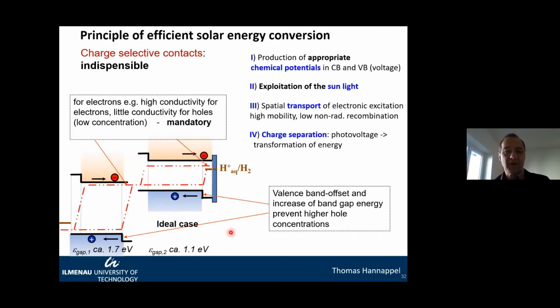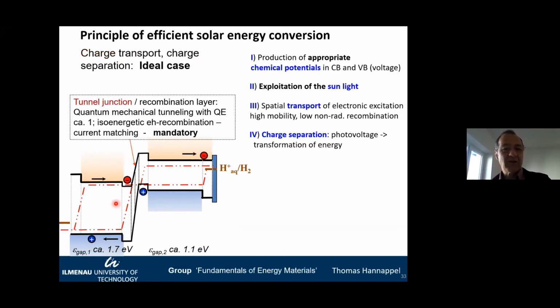Can just suggest to study this. Then also we need tunnel junction, where Esaki got a Nobel Prize for the invention of the so-called tunnel junction. And then we have the perfect device, as you can see, with very good photoabsorbers, with very good charge selective contacts, and with a perfect tunnel junction here, where we have isoenergetic recombination. And if everything is perfect, we can reach highest efficiencies up to 25 or even higher solar to hydrogen efficiencies.